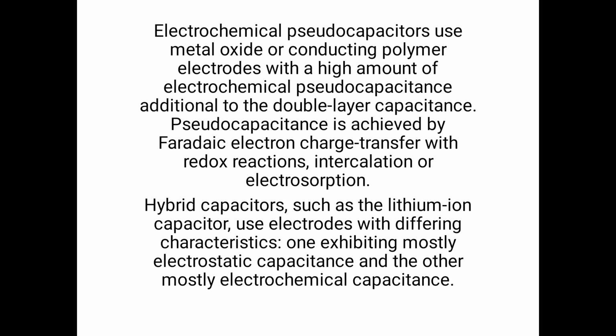Electrochemical pseudocapacitors use metal oxide or conducting polymer electrodes with a high amount of electrochemical pseudocapacitance additional to the double layer capacitance. Pseudocapacitance is achieved by Faradaic electron charge transfer with redox reactions, intercalation or electrosorption. Hybrid capacitors such as the lithium ion capacitor use electrodes with differing characteristics, one exhibiting mostly electrostatic capacitance and the other mostly electrochemical capacitance.